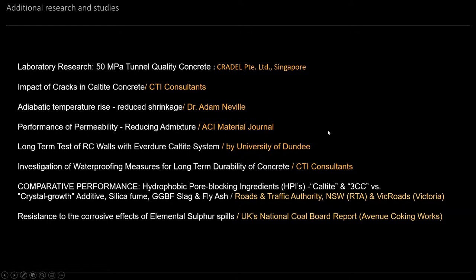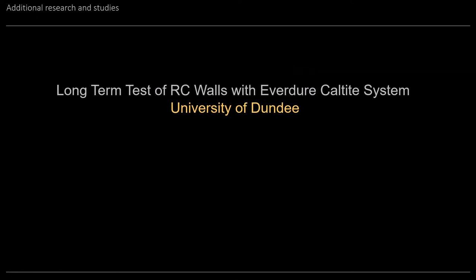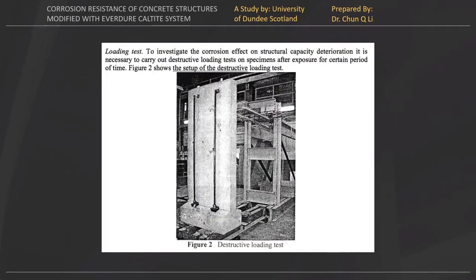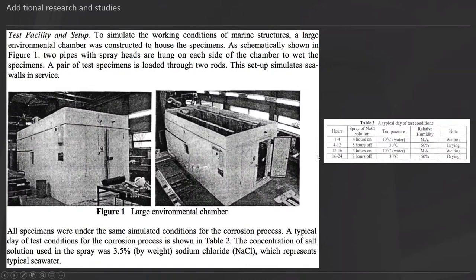So we're going to look at some of the long-term research, or some of the academic research, first of all, and just look at some of the benefits, independent data that we've amassed over the years. So this is the first one I'm going to show you, the University of Dundee. And what they've done here, they've taken some panels, which some incorporated an HPI, some are plain concrete. They're relatively thin, they're fairly modestly reinforced, and they're loaded in this contraption to actually bend them almost to breaking point. And then they're put inside an environmental chamber, sealed environmental chamber, where they're sprayed with warm salt water and dried out very rapidly in a cycle 4 times a day.